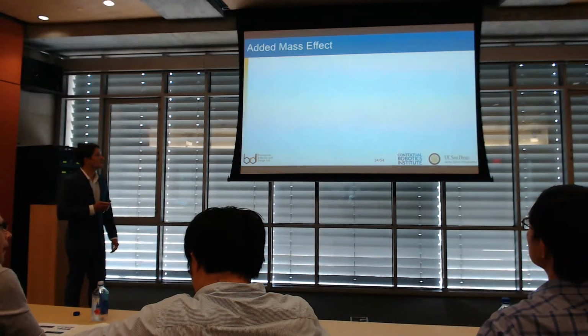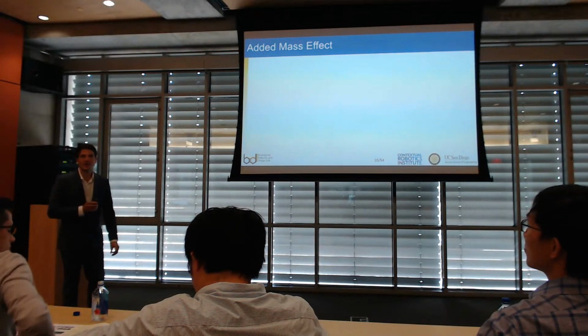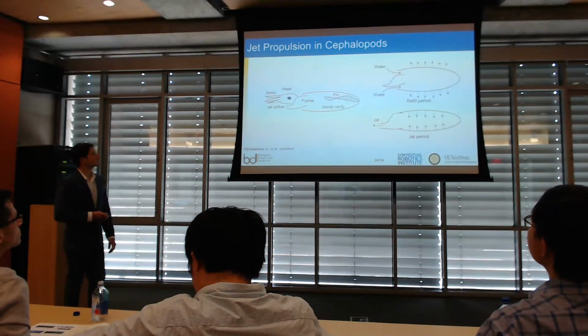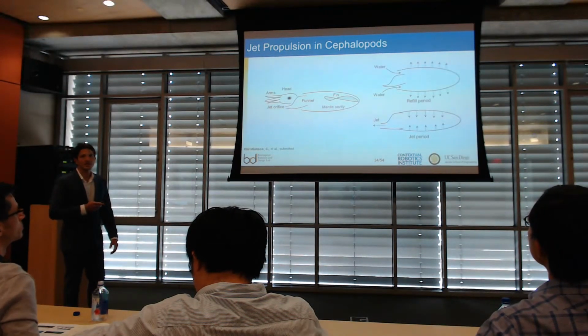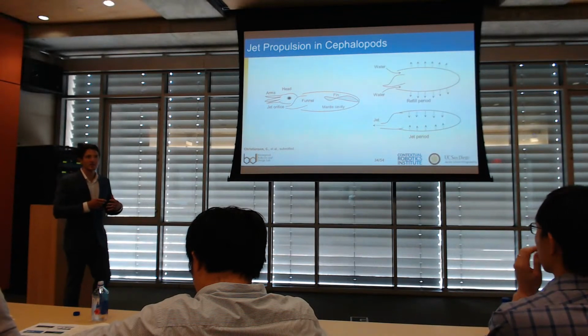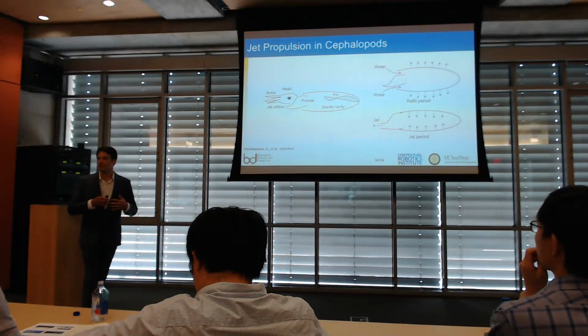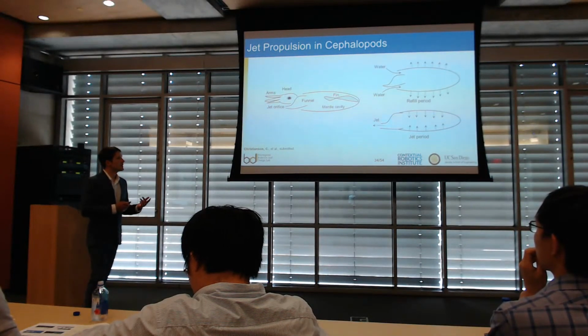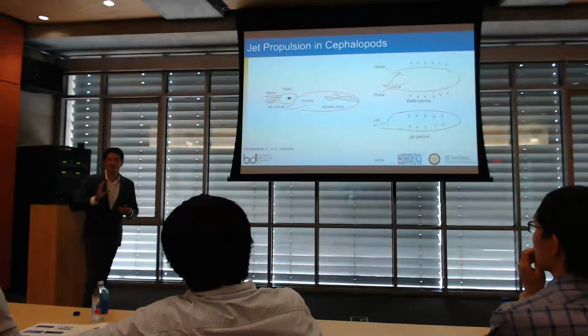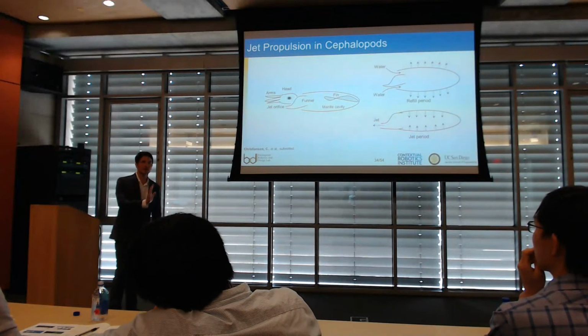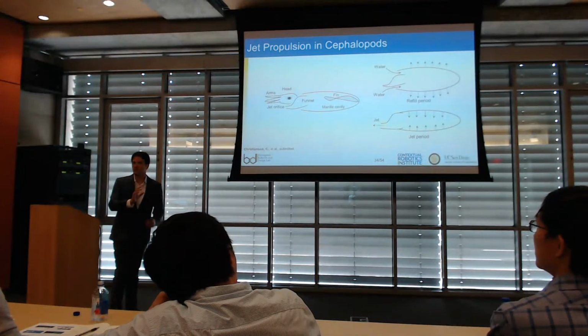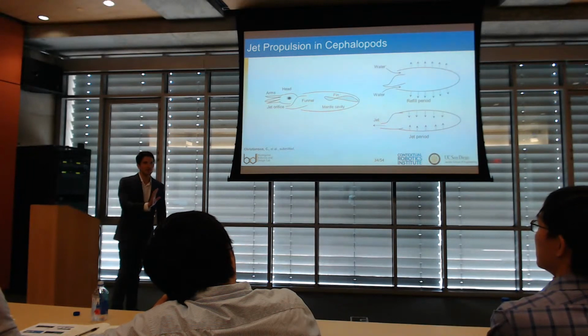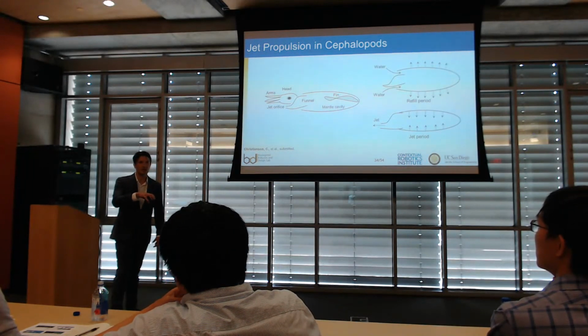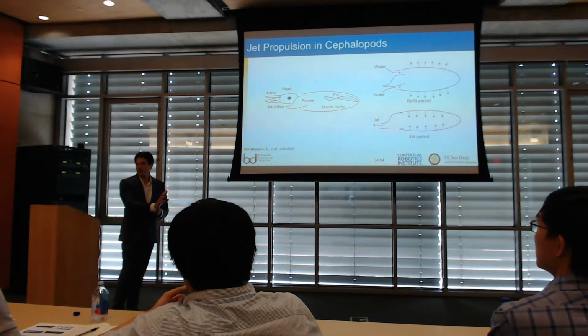I briefly talked about it earlier, the added mass effect. One of the advantages of having a body that can change its shape during swimming is that you get this additional acceleration based on the change of your mass, or your volume, really. What happens is that if you're pushing a body through the water, say you're pushing a ball through the water, if it's a big ball, it's hard to push because there's a lot of fluid that you're accelerating. If you push a smaller ball, you're accelerating a smaller amount of fluid that the ball is displacing. And so if you can dynamically change the size or the volume of the object that you're pushing through the water, you actually get an acceleration from that.